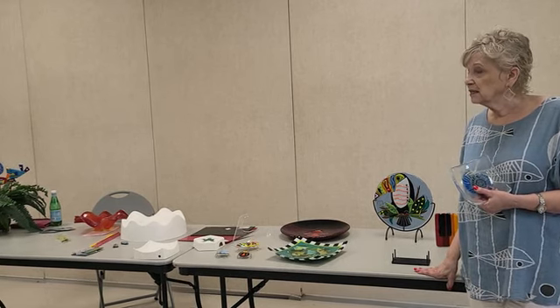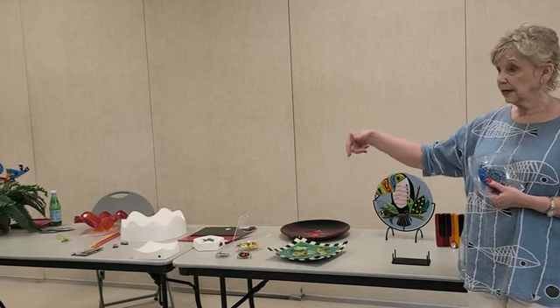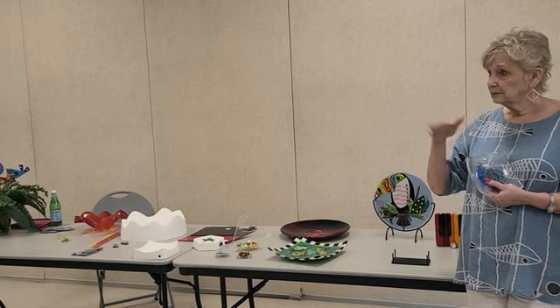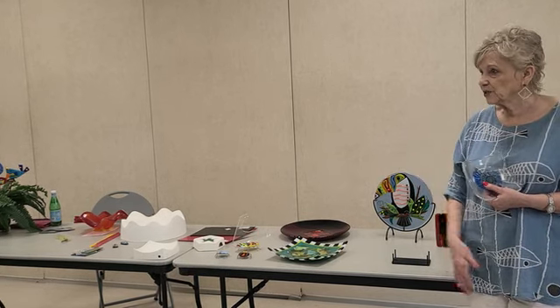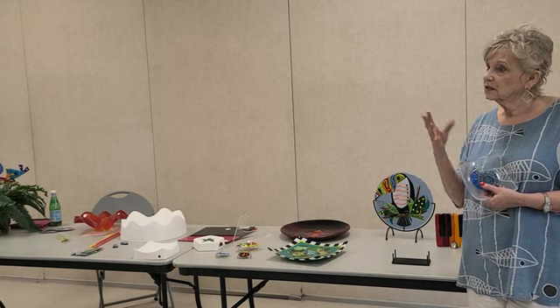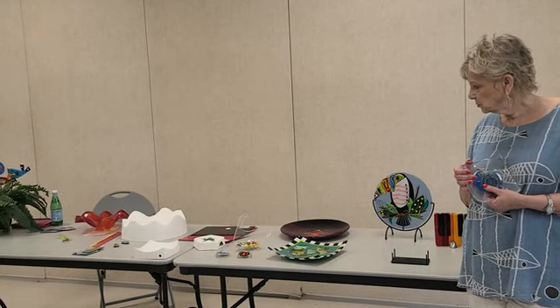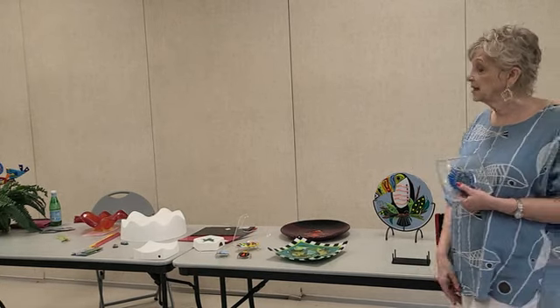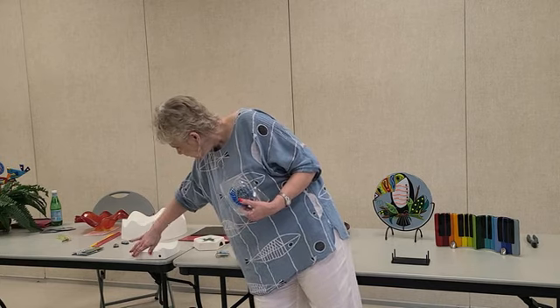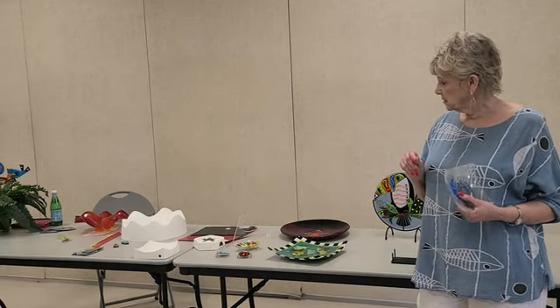Oh, there's another thing on these kinds of things. You can use something called kiln wash, like you can put on your kiln shelf as well, that you paint on, and it's a separator. It just protects it. In other words, it can stand the heat of the glass without changing what it is. Also, that's a lot cheaper. So that's why you'll see the drips on here where I've painted it on. It's pink when you paint it on, and then once you fire it, it turns to that powder stuff. But you can use it several times on this.